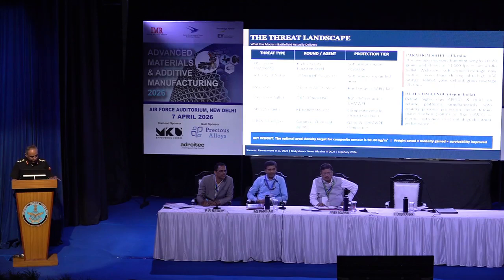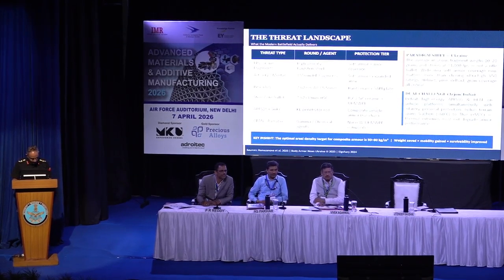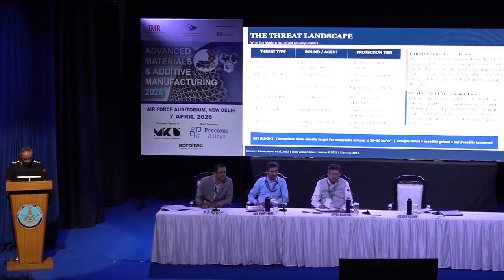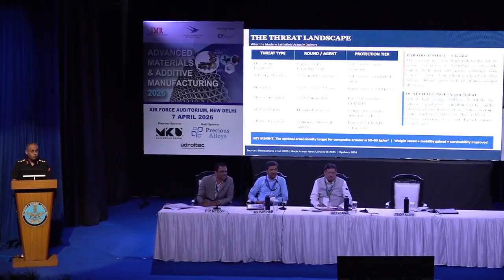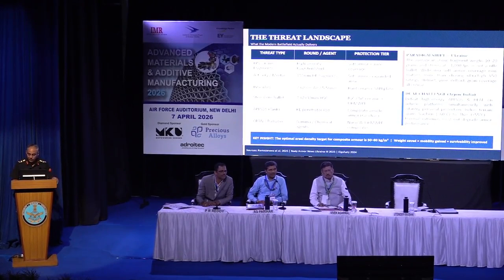At the vehicle level, we have 125 mm armor piercing fin stabilized discarding sabot, that is APFSDS, kinetic energy penetrator, the domain of Kanchan composite on Arjun. At the CBRN end, gamma radiation, chemical agent, tungsten nanoparticle composites are the frontier response. So the paradigm shift that has taken place from the Ukraine lesson is not that we need hard ceramics. It is that we need wider coverage.